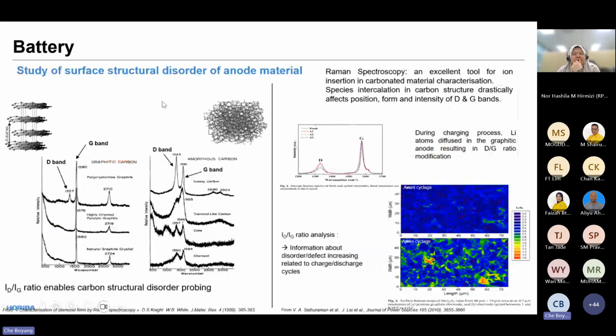So another example here is on anode material. Anode material is usually the carbon materials. For carbon material, we'll study the DG band. And the DG band ratio is actually a parameter to determine the disorder or the defect of your carbon material. So you can do the Raman mapping before and after the cycling of your battery. And you can see after the cycling of the battery, the DG band ratio increases quite obviously, and actually indicates that during the cycling, it gives more defects in the anode material structure.